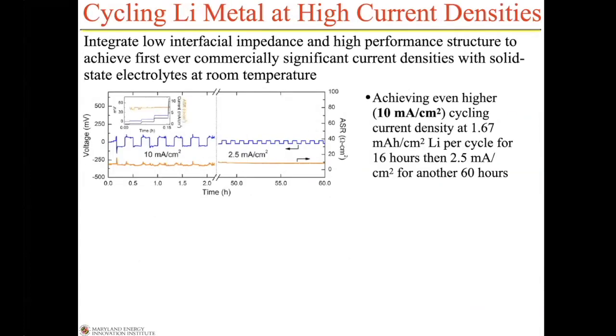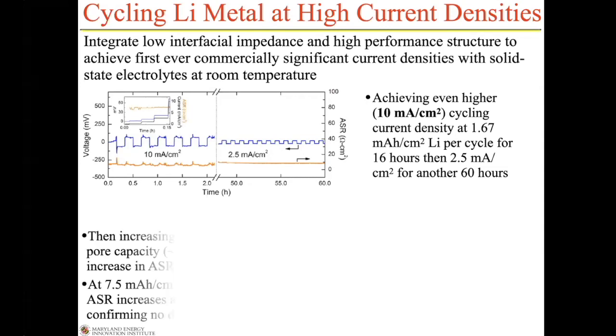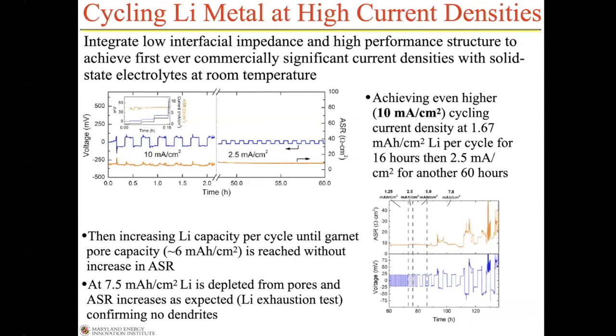So we've taken it beyond that. This is now data at 10 milliamps per square centimeter. Again, very stable cycling. And what we did with this one is we ran it for hundreds of hours. We switched over and did the same thing where we increased the amount of lithium cycling on each pass, but in fact took it all the way to 7.5 milliamp hours per square centimeter.